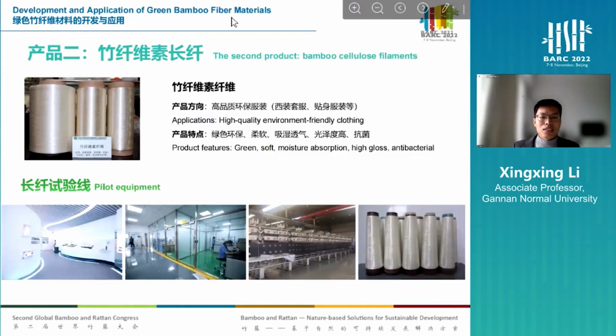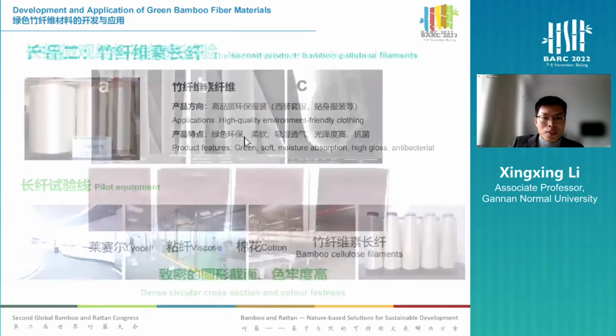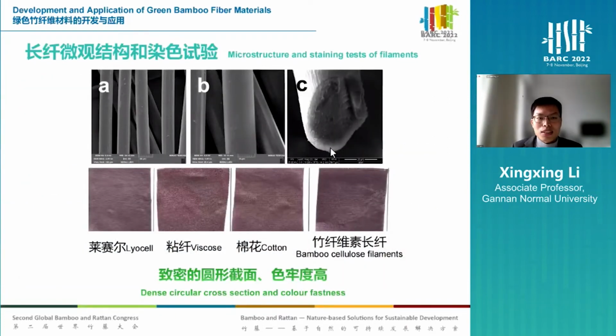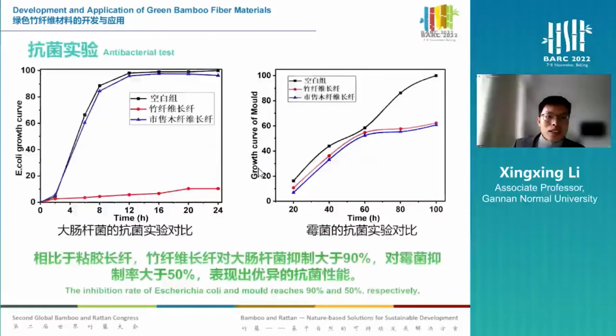And the second product of our lab is the bamboo cellulose filaments. This product has been experimented on the pilot equipment, and this textile is green, soft, moisture absorptive, high gloss, and antibacterial, and can be used for suit production. Our experiment shows the section of the fiber compared with other types of fibers. So we can see actually the dense circular cross section and the color fastness are superior.